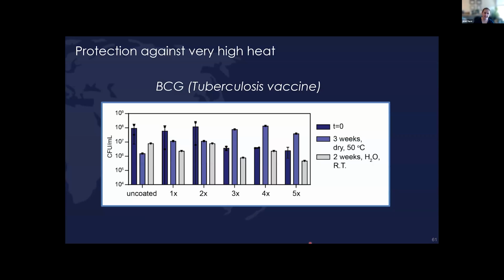And what we can do with this is protect against everything from very high heat. What's shown here is the tuberculosis vaccine, which is just a microbe. This is also used as a bladder cancer treatment. And we can see that if we dry down these microbes, we can store them at 50 degrees Celsius, around 130 degrees Fahrenheit, for at least 3 weeks. That's this light blue bar. And all we're looking at here is just changing the number of coatings. So as we increase the coatings, we also increase the stability here, and that gives us more protection against stressors.